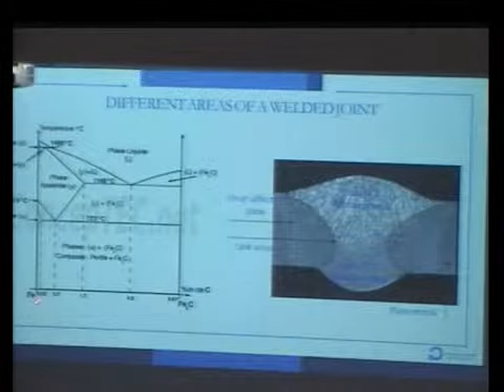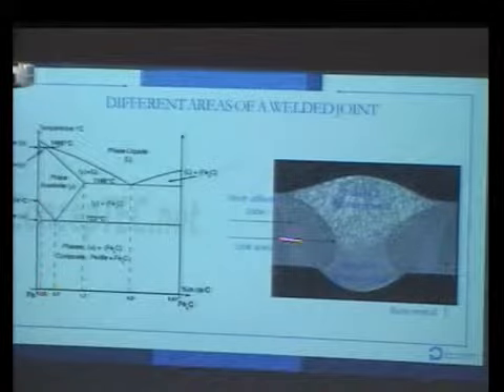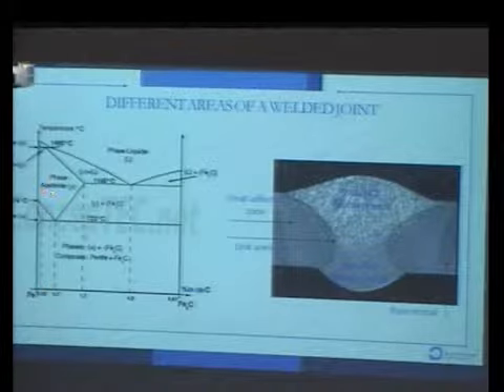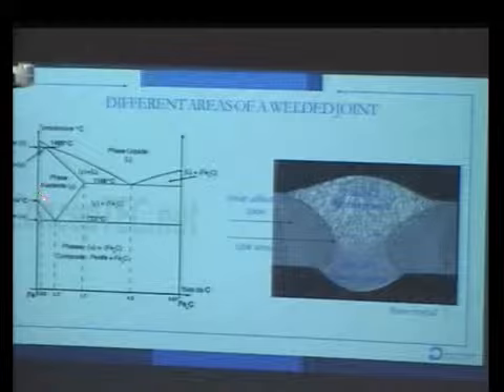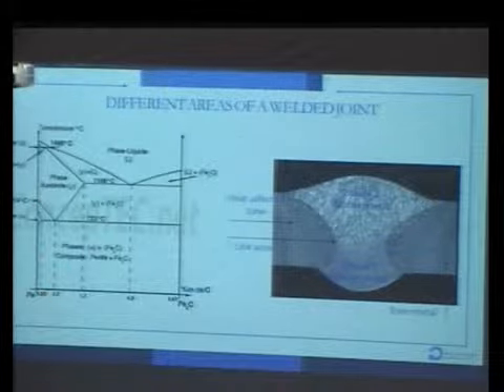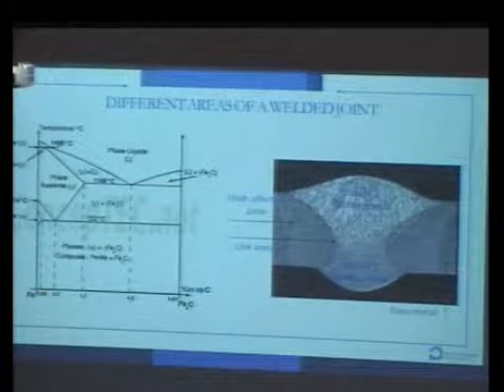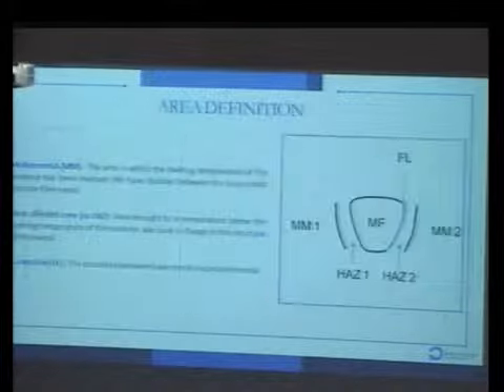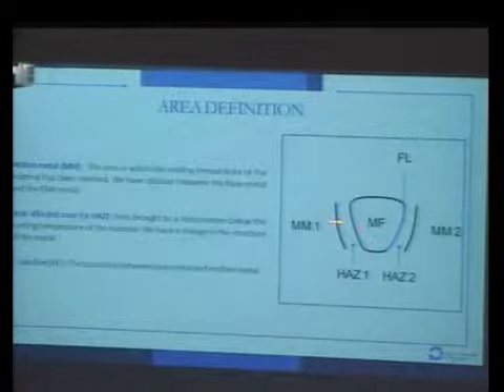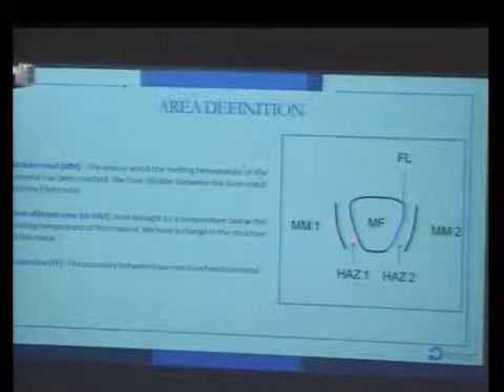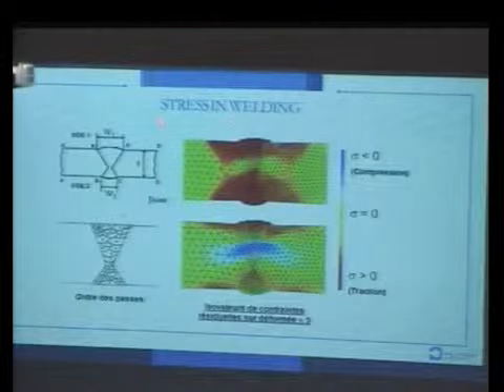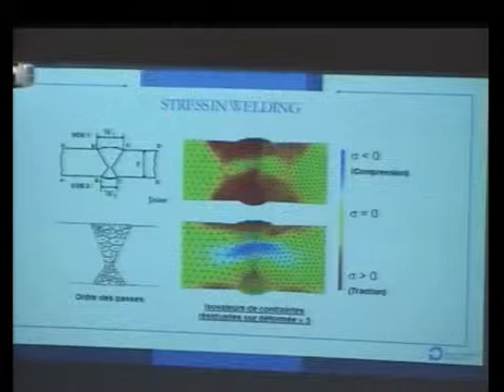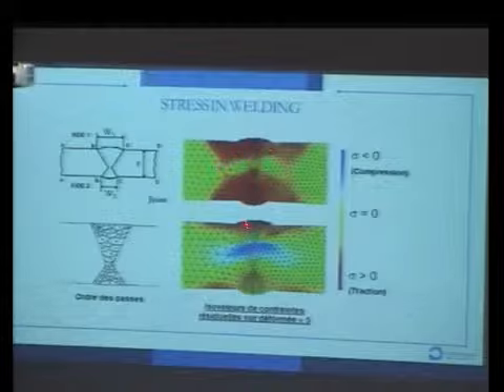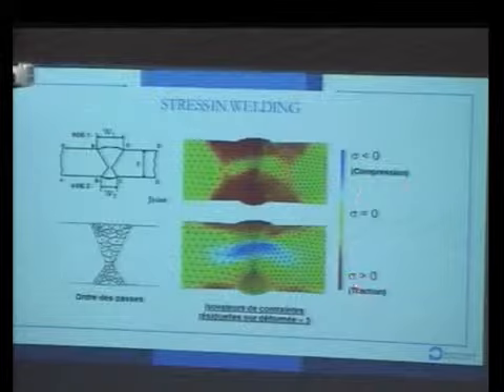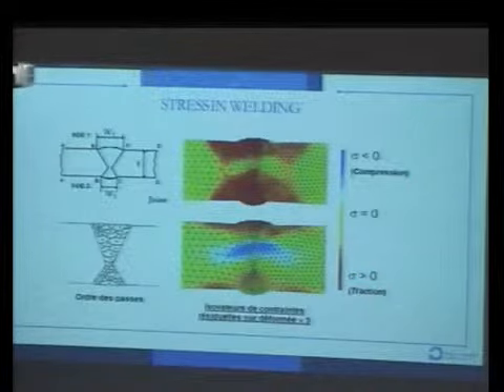And if you take a steel, a low carbon steel we use in welding, you see that at this time you go up here into the austenite phase, and if you cool rapidly, you can have a risk of quench. So here, don't forget the melted zone, and on each side of the melted zone you have a risk of quench, and it could be very different. When you weld, you have stress in welding. I say you have deformation, and during the welding you have different stresses, compression and traction, and that will make deformation or stress inside the weld.